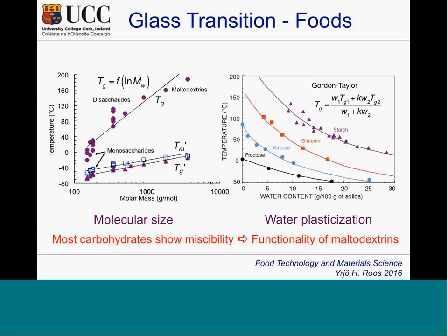So the glass transition of foods happens over a broad range of temperatures. Some generalities: we find the glass transition for sugars. They are nice glass formers, easy to follow. We can see the water plasticization easily. And if we plot the transition temperature of the dry substances against the logarithmic molecular mass, we have a nice linear relationship. Just as with the protein transitions, Tg prime is the glass transition onset of the maximally concentrated solid phase. And Tm prime is the temperature where, in a maximally concentrated system, the first ice crystals start to dissolve. So it's an onset of ice melting.